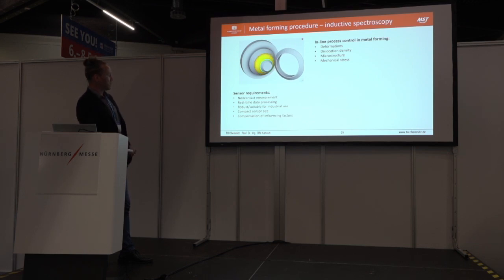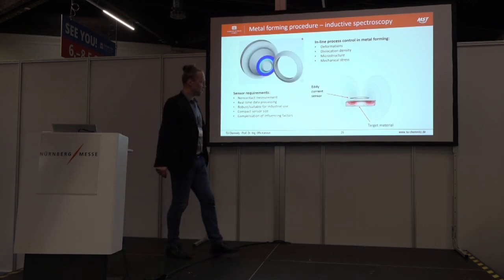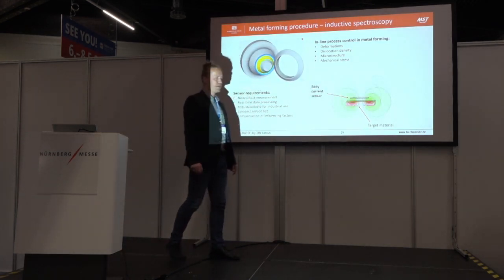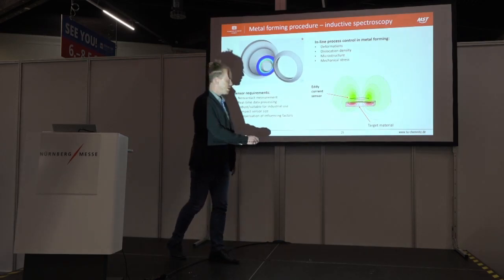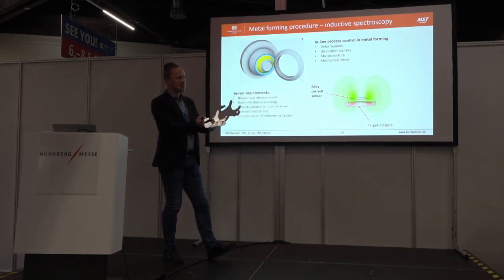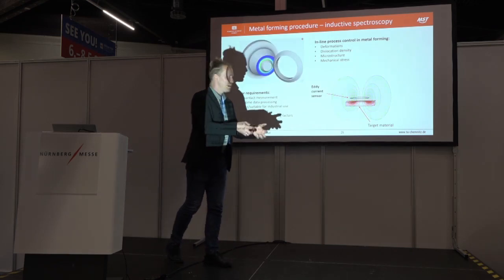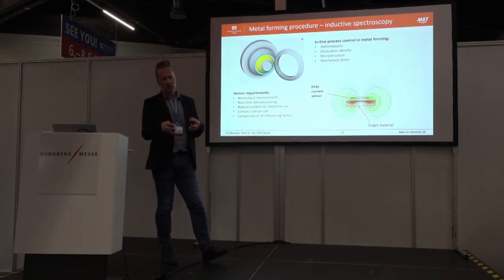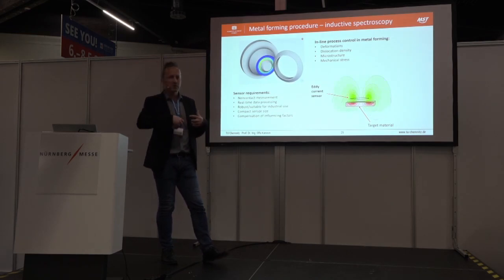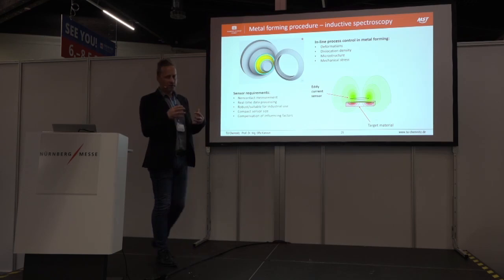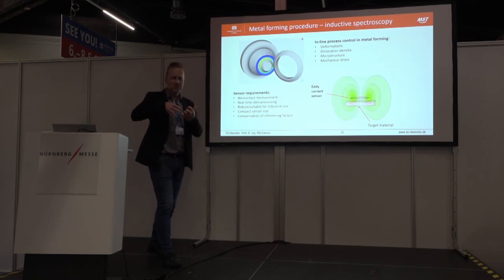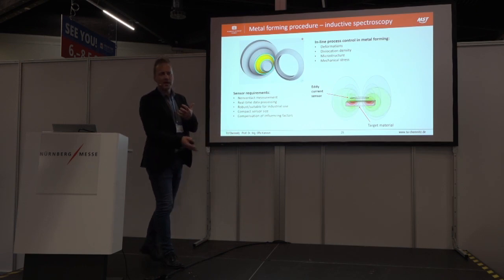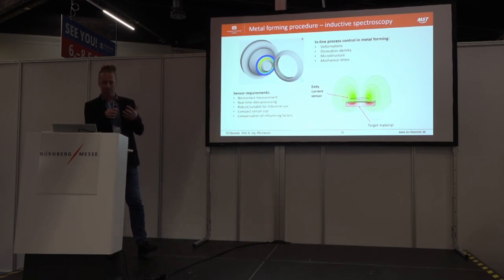And here we also developed inductive sensor approaches, contactless, in real time, very robust and in a compact size, and it's very interesting. We use the eddy current effect. We have a coil. The coil produces a magnetic flux, a magnetic field, which goes into a target material. And here we also use, as I said, the approach with multispectral information. A lower frequency causes an eddy current which goes deep into the target material. A higher frequency only scratches the top, the so-called skin effect.